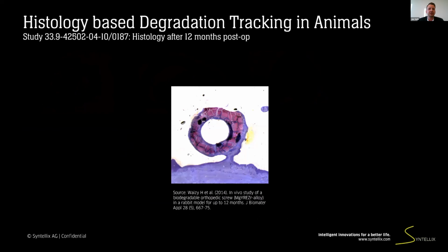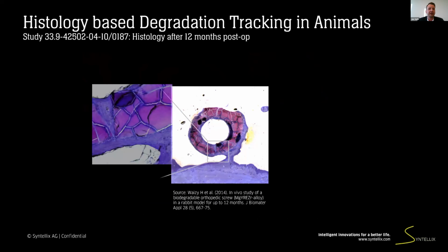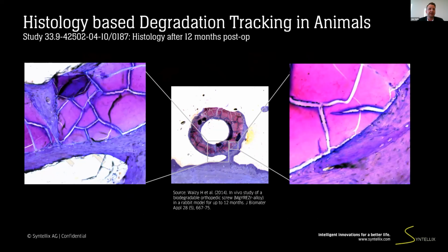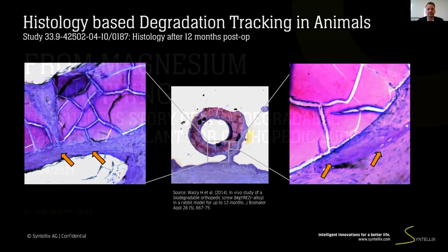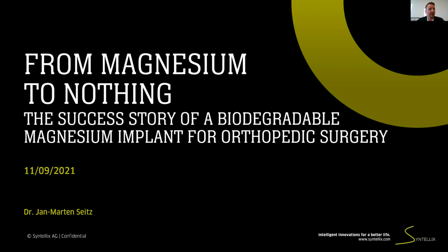Within the magnification of the histological image, one can clearly see the bone cells penetrate the former implant site, actually turning the device into new bone. You can actually see the magnesium hydroxide segment that remained after corrosion of the implant's wall is penetrated by such bone cells. Knowing this, we actually have to rename this presentation, as magnesium will not turn into nothing, but into bone.